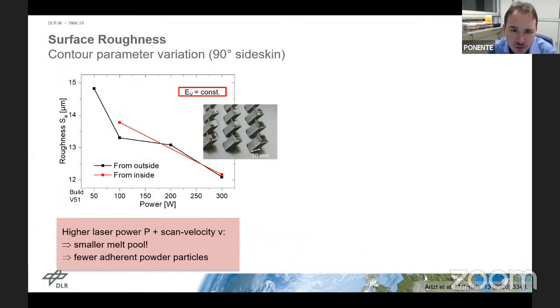So we've done that on different types of specimens that have different surfaces: up skin, side skin, down skin, vertical thin walls, and things like that. And actually, there is quite some possibility to optimize parameters here. You see a trend here that by increasing the power on the contour line, you can reduce the surface roughness from roughly an arithmetic mean surface roughness of 15 to roughly 12, just by changing the laser power and the scan velocity in combination, such that the volume energy density of the laser track still stays constant. So increasing laser power means also increasing the scan velocity accordingly.